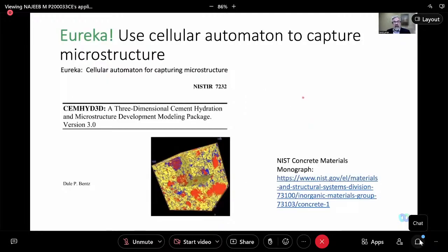And that better idea came along with other NIST researchers. Dale Bentz and Edward Garboczi had this cellular automaton idea where you basically just build your volume out of voxels, and all the voxels have identity as being a certain kind of cementitious material, and the interface would determine what rules were applied for converting that in the next time step. So hydration would take place only at the interface, and the volumes would change from one product to another. The rules were very simple. The calculation problem was very simple. And so all the complexity of tracking spheres and little slivers was taken away. And we were thinking about a more simple, easy, faster way to compute this problem.